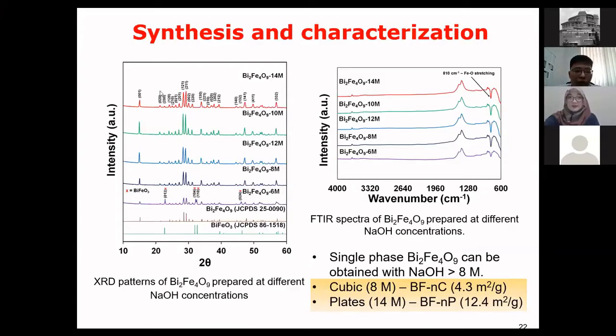So this is the XRD. This is how Prof. Karna has already explained a bit on how we can use XRD to characterize the materials, the catalyst. For our XRD results, we found that this is indeed bismuth ferrite. But if you don't use the correct amount of base or sodium hydroxide, you will not end up getting bismuth ferrite, Bi2Fe4O9. You will get something else. So controlling the sodium hydroxide concentration is very important.